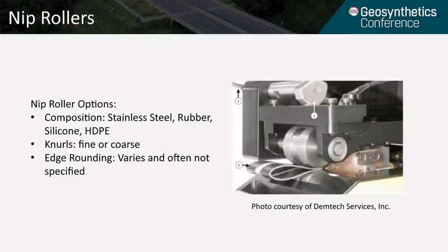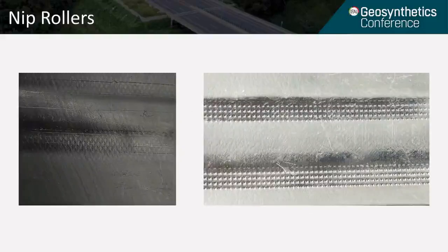Once the heated material passes through the wedge, they're going to be forced together using the nip rollers, and like the wedge, the nip rollers come in different compositions, such as stainless steel, rubber, silicone, and HDPE. There's also different knurls, such as fine or coarse, and there's also different edge roundings, and the edge roundings are often not specified, but can make a huge difference, especially on thin materials. This slide shows some different impressions left by the different nip rollers of different manufacturers.